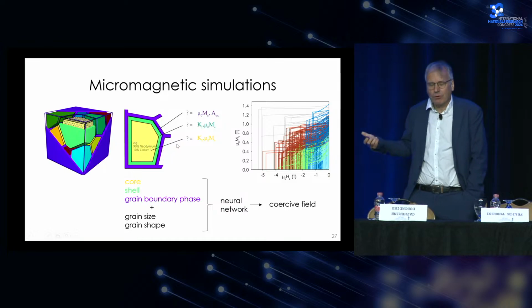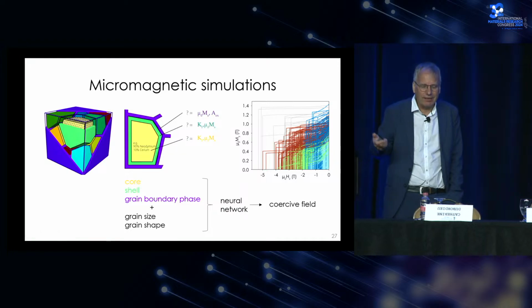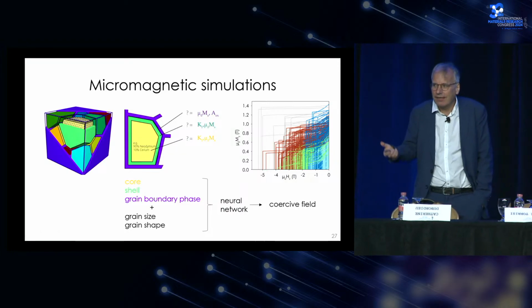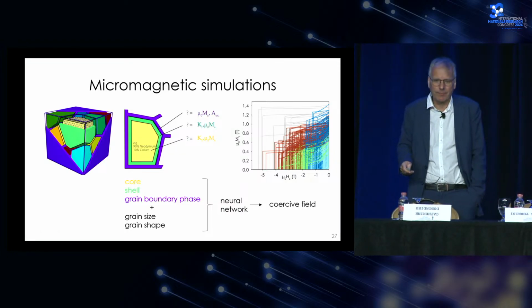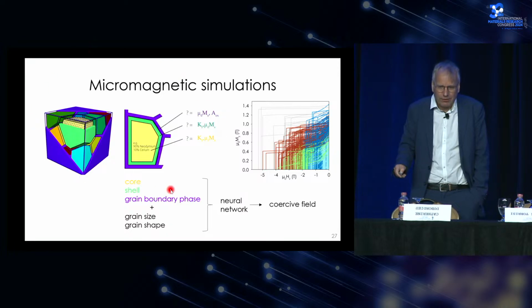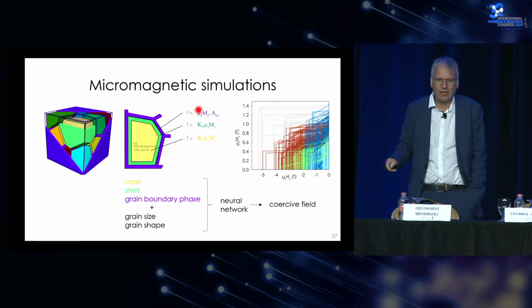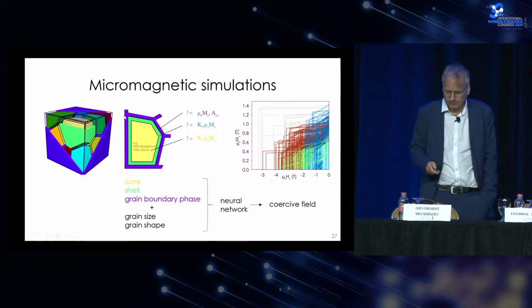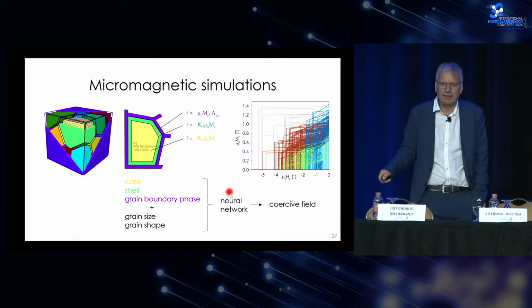And what we can do the very same. We can generate a lot of data and then do inverse modeling. So we generated a lot of hysteresis curves by varying the chemical compositions of core and shell, and also the size and shape of the grains and the thicknesses here. And we did so with a very small neural network.